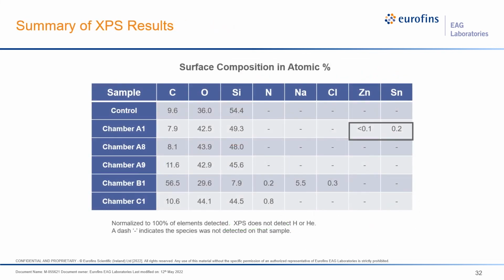So this is the summary of the XPS results. And I just wanted to show that the control chamber is similar to most of these in carbon content, except for B1. B1 has a lot more hydrocarbon here. And then the other chamber here, A1, I want to call out, this is the zinc and the tin, which are very concerning. And then in chambers B1 and C1, we actually had a little bit of nitrogen. And then we also have the sodium and chlorine seen on B1. So these are all the things that we wind up seeing. Everything else that has a dash there basically means it's below the detection limits.